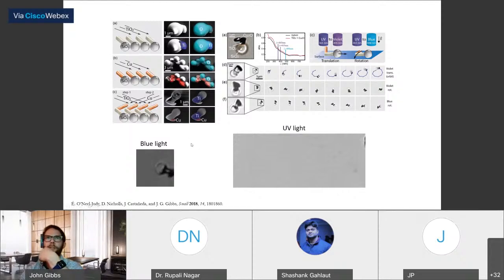And something that's kind of interesting about this too is that if you look at this figure on top here, the schematic C, it's hard to tell exactly by just looking at the microscope images, but it seems like the orientation with respect to the substrate actually changes too when the light turns on. So depending upon how that orientation changes will tell you whether or not you have translational or rotational motion. So I don't want to mislead you and tell you that we only got rotational motion with blue light and only translational with UV, because that's not exactly the case. And I think that's the variations between the samples.